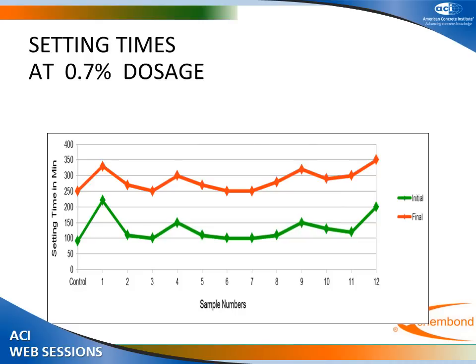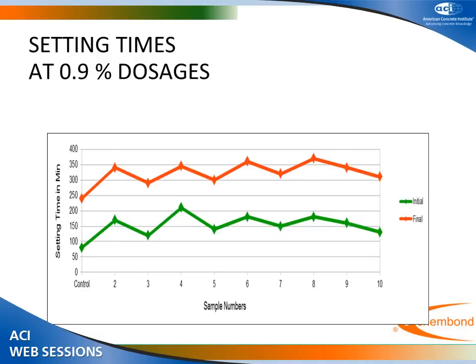So let's go to setting times. At 0.7% dosages, you can see setting times are quite favorable, and they generally meet the standard ASTM C494 type G. At 0.9% dosage also, you can see that the maximum retardation is around 3 hours. So that means this concrete is workable.